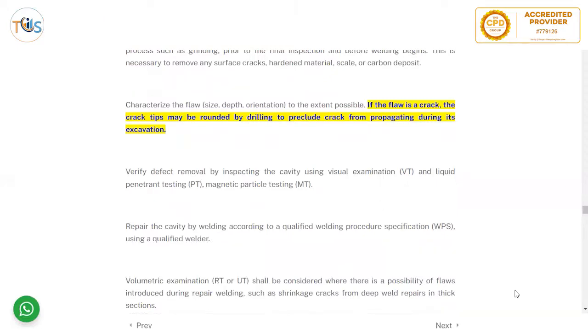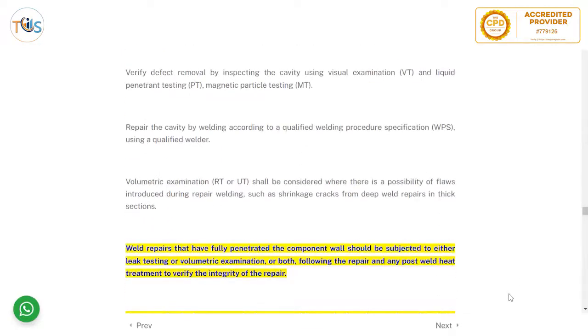If the flaw is a crack, the crack tip may be rounded by drilling to preclude the crack from propagating during its excavation. So first, blunt the crack, reduce the stress riser. A crack has the highest stress riser. It just works as a knife, cutting through. So blunt it and then remove it. Verify defect removal by inspecting the cavity using VT and PT or MT. And repair the cavity by welding according to a qualified WPS using a qualified welder. And then do RT or UT.